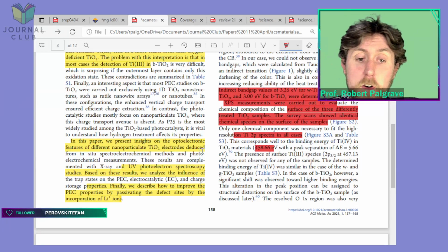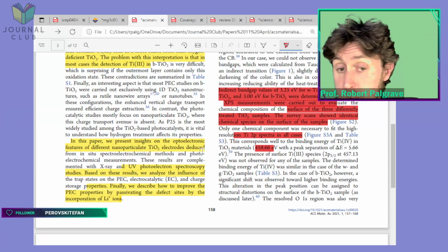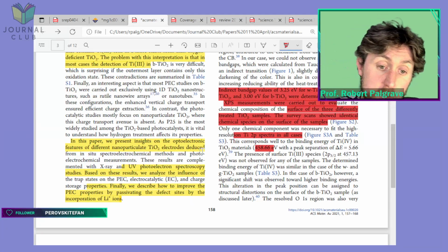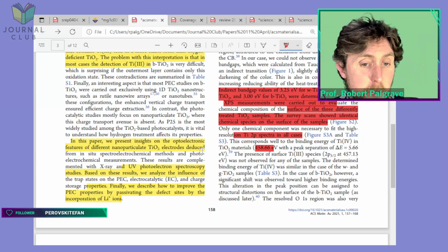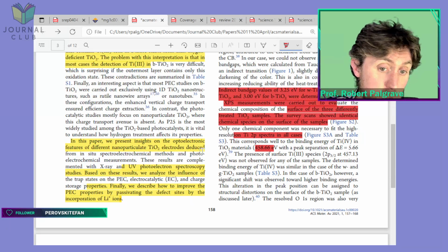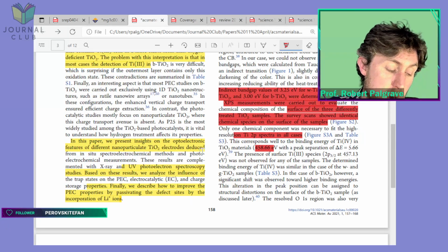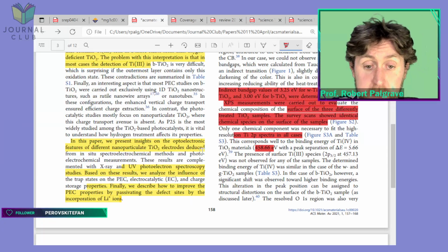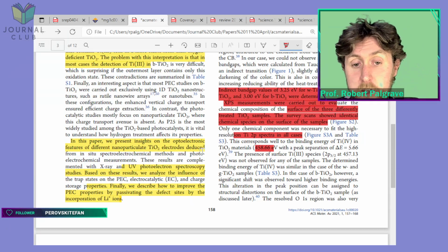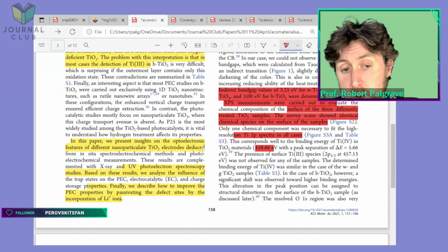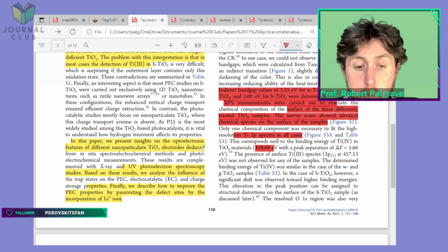the Fermi level. So when you change your Fermi level, you change your reference point, and so you change all of the binding energies. It's not inconceivable that by doping with hydrogen, they are changing the Fermi level and this might cause the change in peak position. I don't know, but it's something that maybe they could consider.